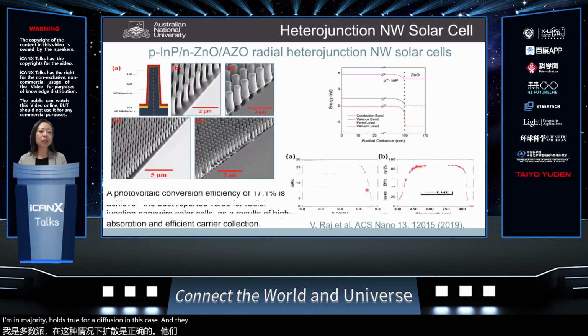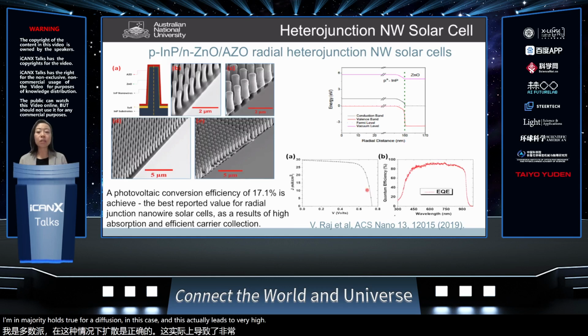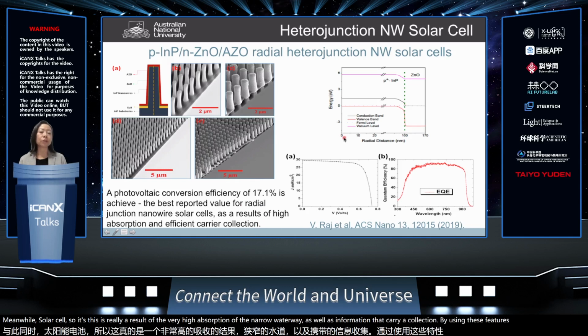And this actually leads to the very high efficiency we obtained in radial junctions. We've demonstrated 17.1% efficiency in our radial junction nanowire solar cell. So this is really a result of the very high absorption of the nanowire array, as well as efficient carrier collection by using these heterostructures.